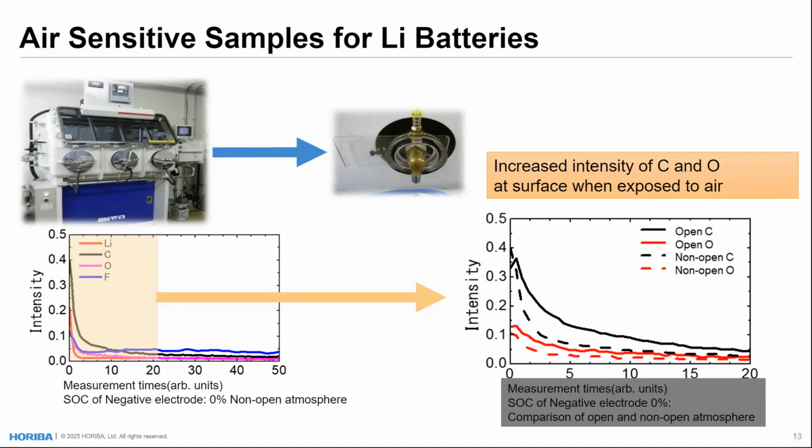The sample was exposed to air, and you can see the amount of oxygen and the penetration of oxygen in deeper layers of the sample. On the left side, you see the profile for the same sample, but in the glovebox without being exposed to air. So this is another tool which we have and can help with special samples which are sensitive to air.